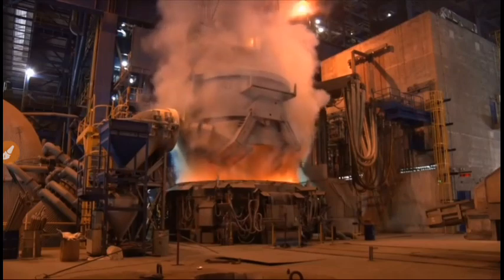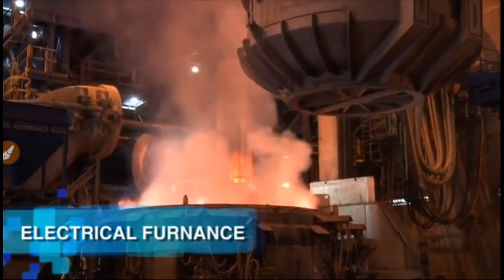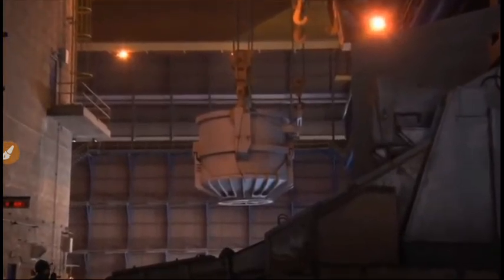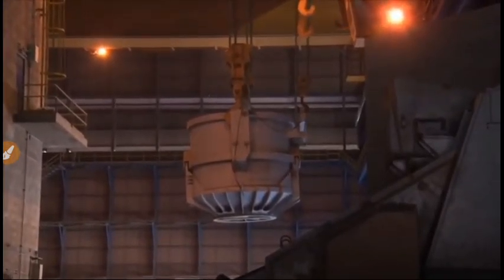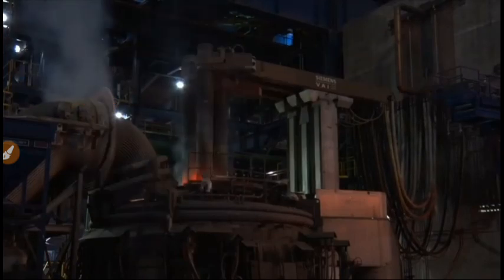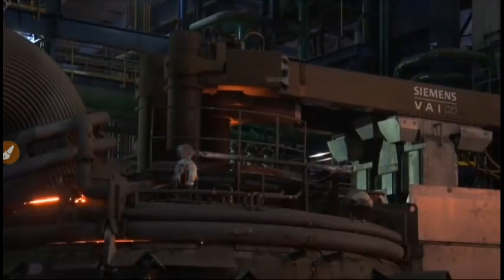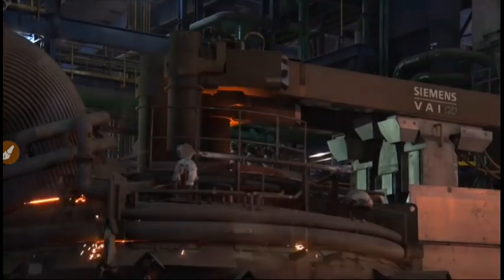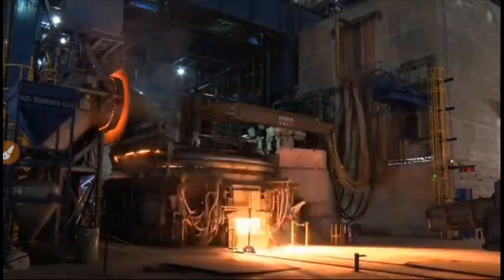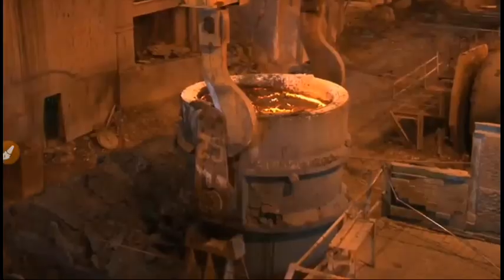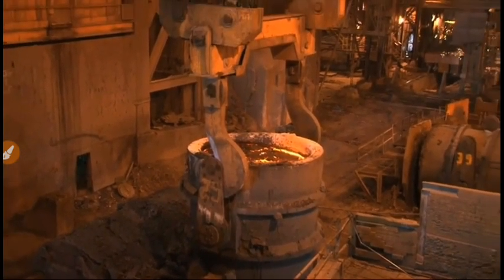Production of liquid steel by means of the electric arc furnace is conducted by beginning with a mixture of scrap metal, iron briquettes, or liquid pig iron at a rate of 150 metric tons per casting. Scrap and briquettes are loaded by using baskets, while the pig iron is transported by a gutter to the furnace, where 3 graphite electrodes apply 140 megawatts of electric energy to melt the load and produce steel, which is emptied into special ladles.